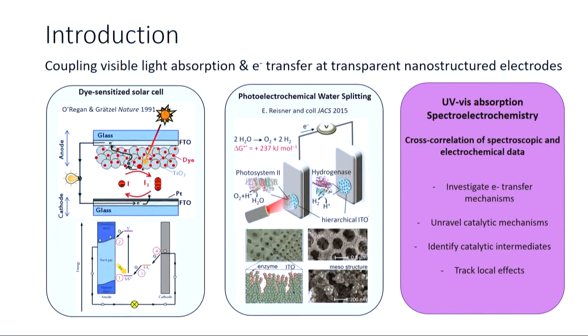So the second example I really like for this application of transparent nanostructured electrodes is the one that was published a few years ago by Erwin Reisner's group. And it's about photoelectrochemical water splitting. And in this specific case, what they use is a transparent, fully conductive porous electrode made of indium tin oxide that is used as a transparent conductive support to immobilize enzymes. And the two enzymes immobilized are, on one side, photosystem 2 and, on the other side, hydrogenase.